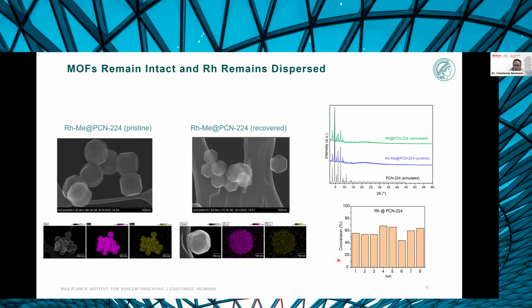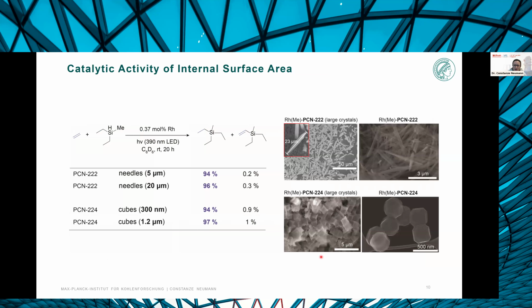And importantly, also after the catalysis is done and the catalyst is recovered, the rhodium sites remain well dispersed and the PXRDs look unchanged from the material that was present at the start, which increased our confidence that we were truly looking at the catalytic site that we had planned and not something that is a decomposition product of the original catalyst. And the rhodium catalyst can also be recycled several times without any systematic decrease in the yields. We also looked at making larger MOF crystallites in order to confirm that the catalysis was actually taking place in the pore like we had imagined in the design, rather than simply on the surface of the material. And we don't observe any decrease in the yield when the crystallites become larger.